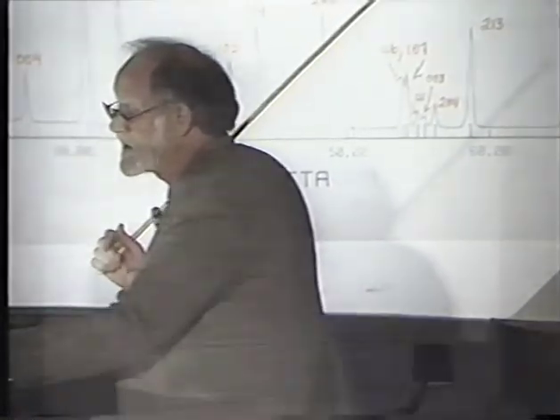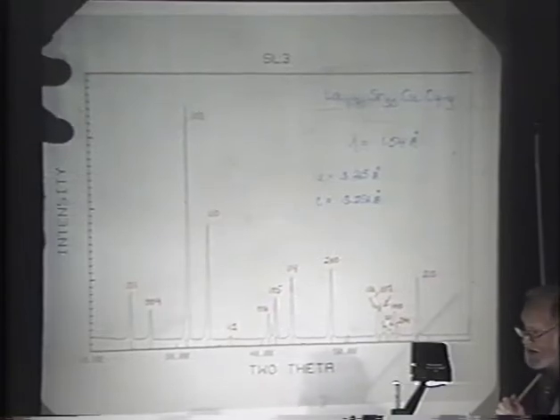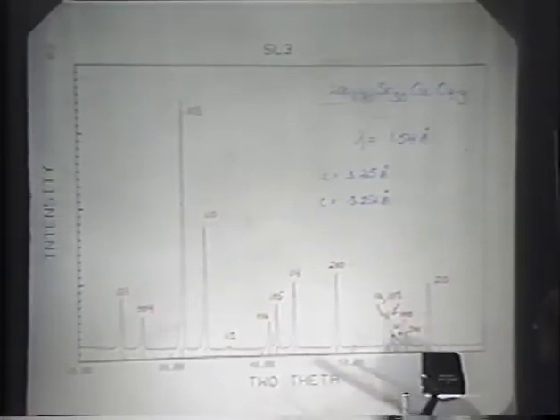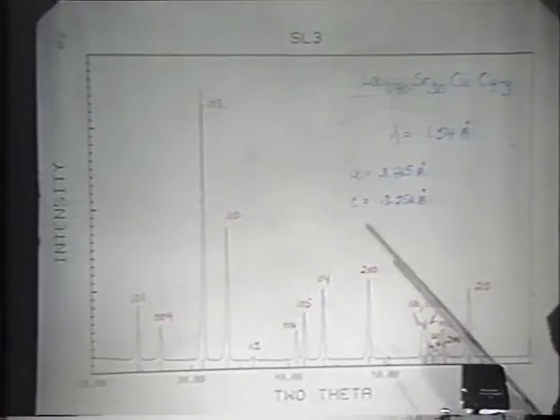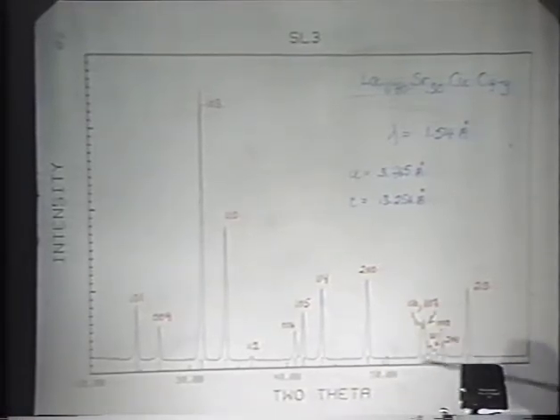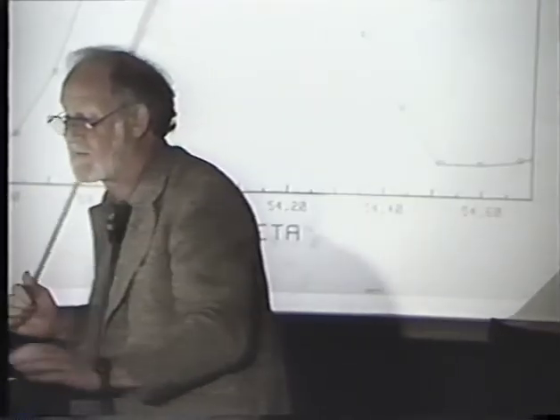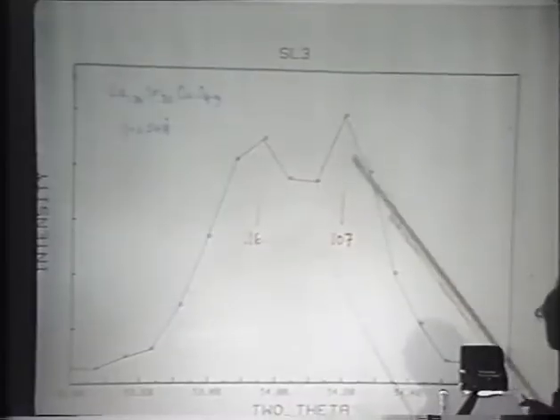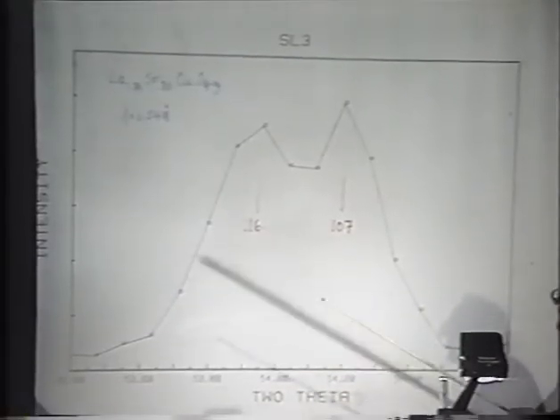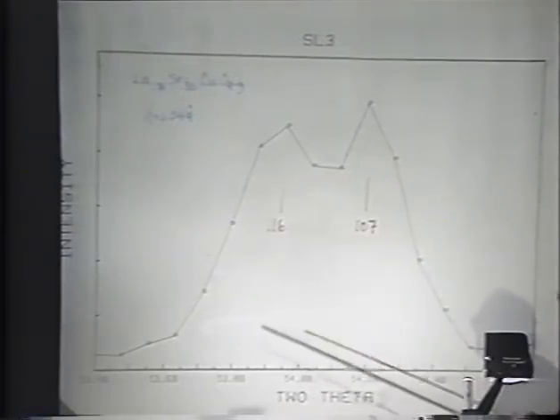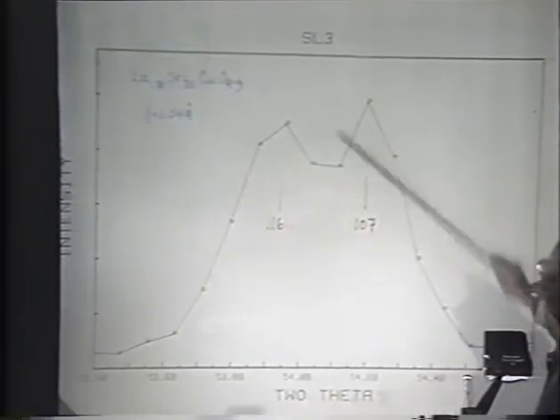Just to give you a feeling for the technique, I show here a typical scan. It turns out to be from the lanthanum strontium, not lanthanum barium sample, but it's a typical scan showing the pure tetragonal phase, the potassium nickel fluoride phase. And consider this set, the 116 and 107, the closely spaced peaks. And if you blow that up, you'll see that they have a profile like that. And we can improve that a bit in our own lab by having tighter slits and better collimation and so on, and could bring that down like so.